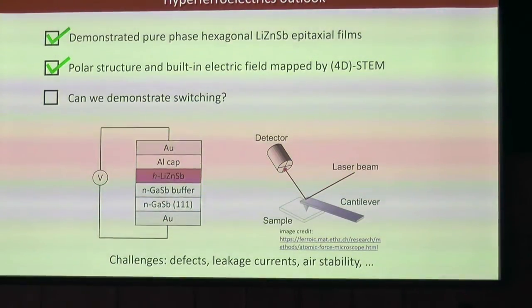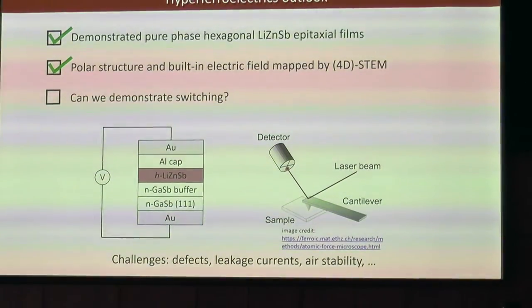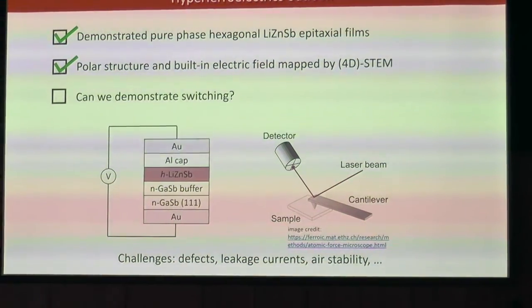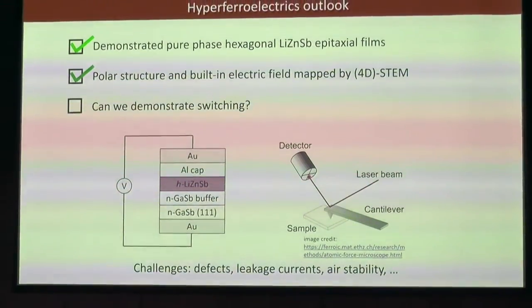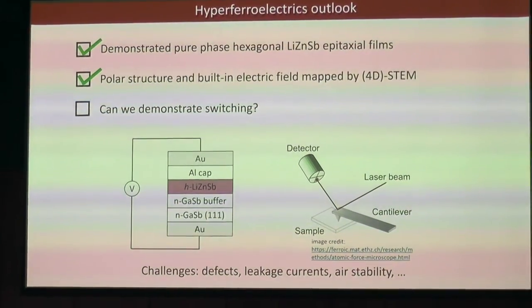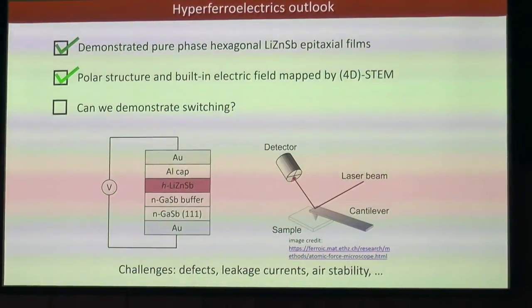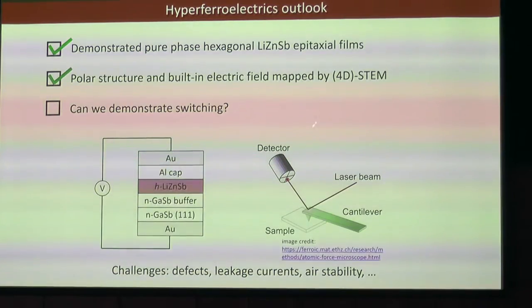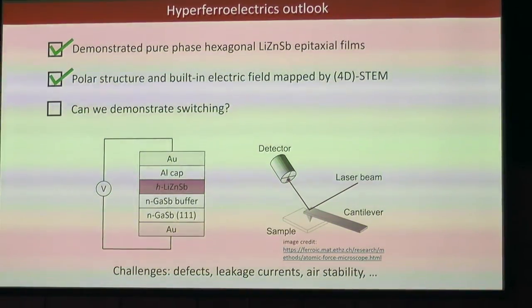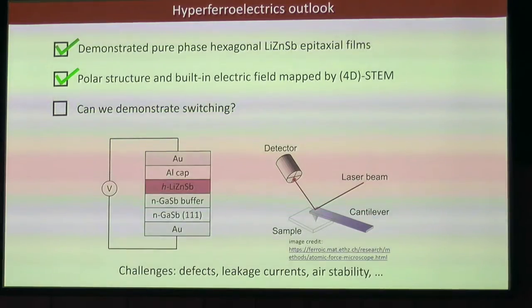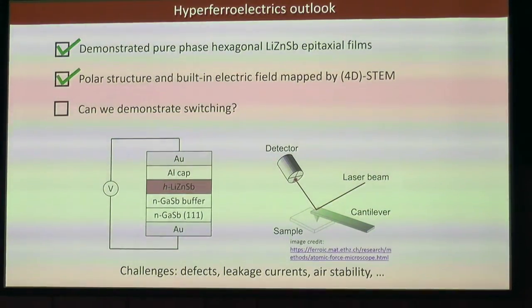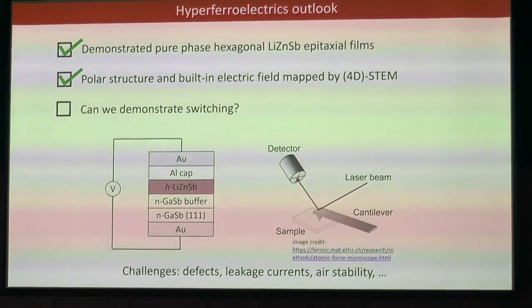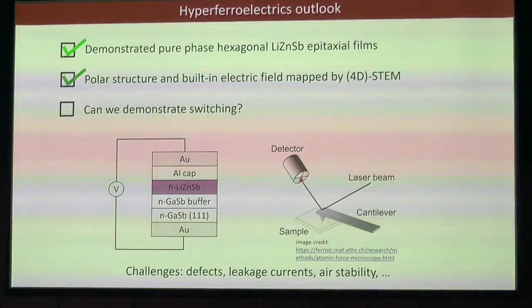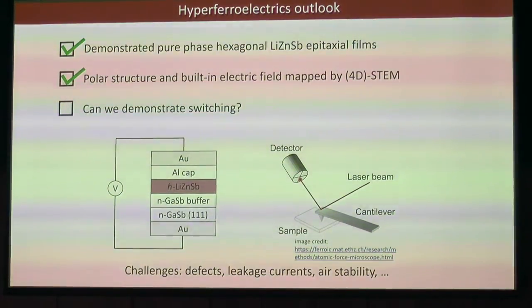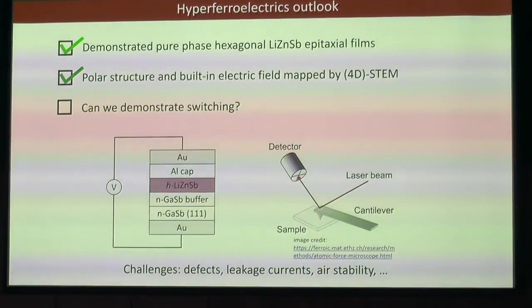Okay, so for this first part, we've shown at least that we know how to control the phase purity of these samples by lowering the temperature in MBE growth. I'll say right up front, these are the first epitaxial films that have ever been grown of lithium zinc antimony. We can map out built-in electric fields, and the real question is whether we can actually demonstrate switching. So we've been doing a lot of work building up this growth capability in our lab using a very small MBE system. We're going back to Paradigm later next month to see if we can grow clean enough films that we can actually try to switch in a capacitor or switch by PFM.